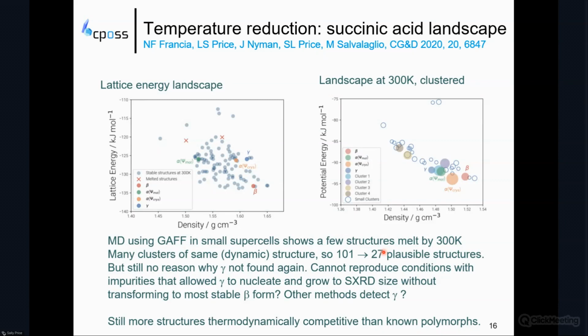of more structures, but the gamma was still perfectly good as a structure, and we couldn't find any reason why gamma was not found again. So it looked as if it cannot reproduce the conditions with impurities that allow gamma to nucleate and grow to single crystal diffraction size without transforming to the more stable beta form. And we'd be very interested if anyone else finds this gamma polymorph in their experiments. But the key result is there are still more structures that appear thermodynamically competitive with the known polymorphs than are known.